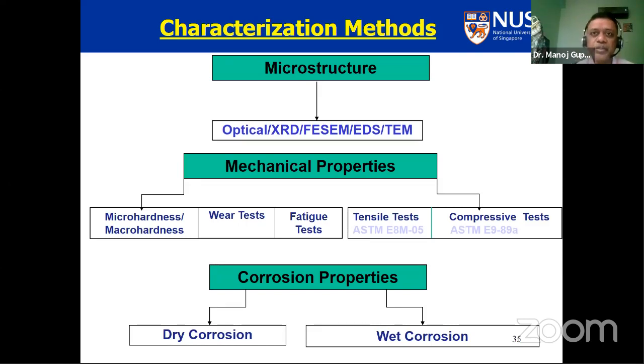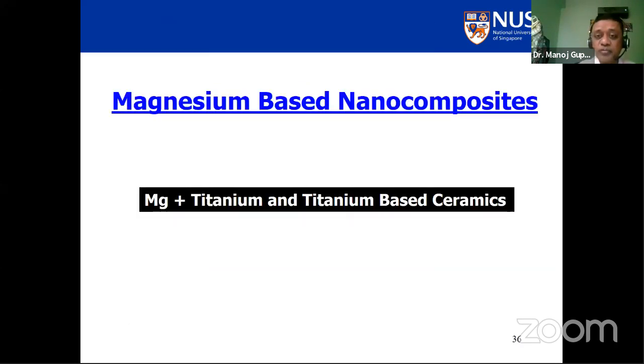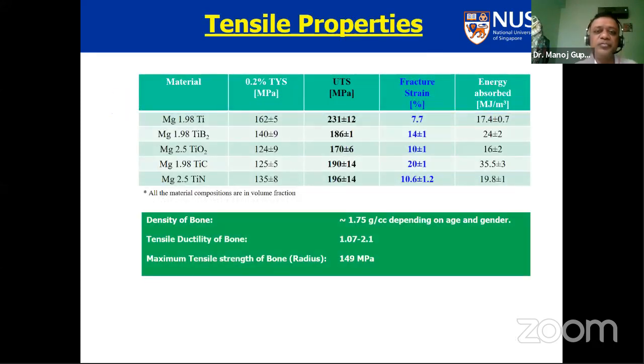Now, once you use the right material and the right processing, you have to characterize it to ensure it really behaves in the way governed by the end application. So let's look at some of the magnesium-based nanocomposites we worked on using elemental titanium and titanium-based ceramics. Why elemental titanium powder? Because it does not react with magnesium and it improves the biomechanical performance of magnesium.